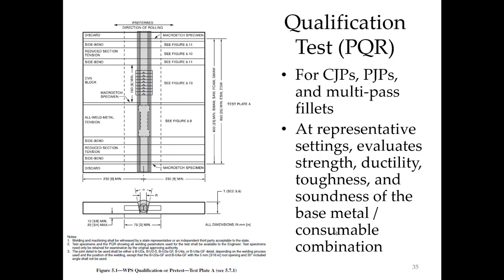So I'll talk in a bit more detail about the qualification test. If you go in the code, you'll see this joint. You'll see that we prescribe a rather open groove that's welded from one side with typically a 1-inch plate. The design of this test plate with a very wide groove and a 1-inch plate is intended to provide a lot of deposited weld metal.